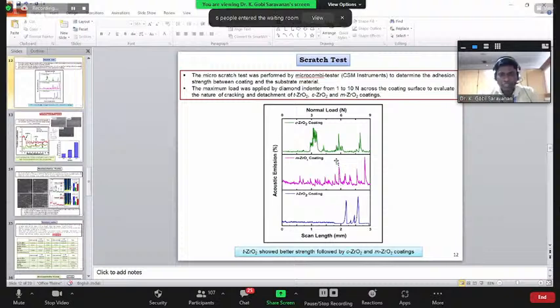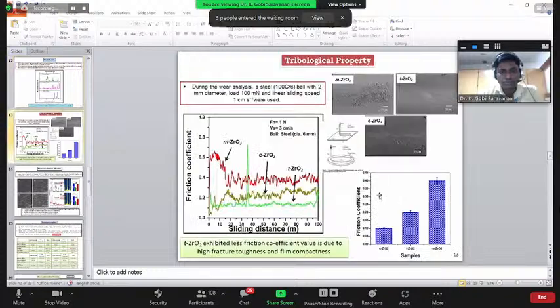So from this, we can conclude that the tetragonal zirconia shows the higher adhesion strength, as well as higher fracture toughness. It is better for the scratch test analysis.